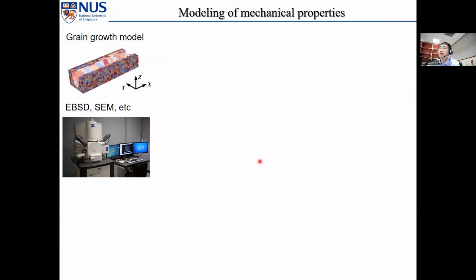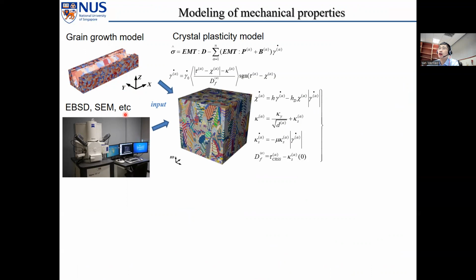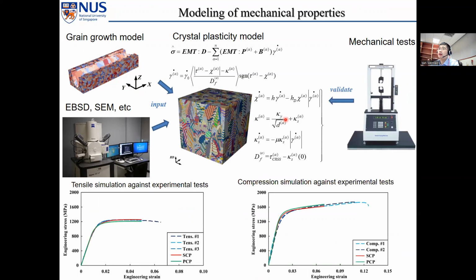So furthermore, with the microstructure model, from either the grain growth model or experimental data, we can construct the microstructure geometry and use a crystal plasticity model to simulate the mechanical behavior and do experimental validation. But here, what I want to show is the importance of the residual stress. And you can see during tension and compression tests for the same batch of samples, the yield stress has a difference of around 400 megapascal for this titanium sample, which is very significant. This is due to the large residual stress in additive manufacturing.